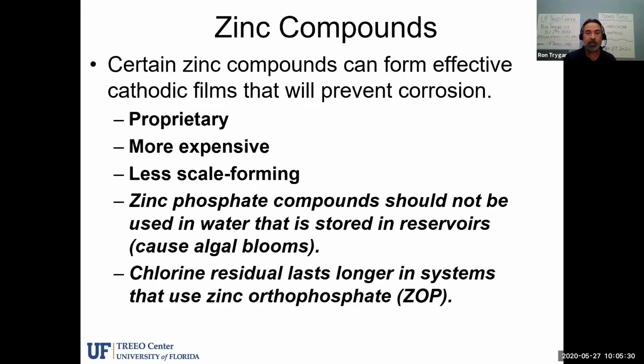They are a little bit more expensive than, say, just adding lime slurry to the water, which we talked about earlier. They are less scale forming. The zinc compounds are less scale forming than, say, adding lime. Obviously, we want to watch out for that, so this might be preferred by your water system because you don't want to form scale. Zinc phosphate compounds that contain zinc and phosphate together should not be used in water that would be stored in a reservoir that's exposed to sunlight, because the phosphorus would actually increase algal blooms. So we generally don't use the corrosion prevention chemicals out in the reservoirs, but that's just something we wanted to make sure that you see there, because the phosphate component would definitely increase algal blooms.